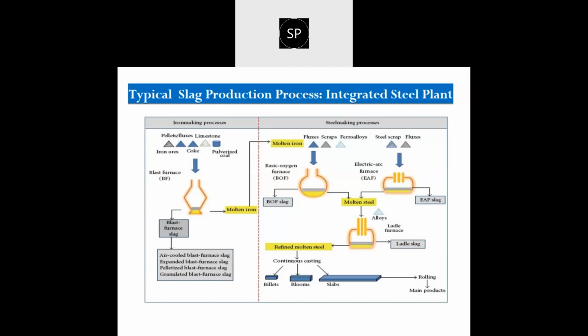In case you want to do cement concrete road work and ground granulated blast furnace slag is available nearby, then you can directly mix this material as a replacement of ordinary Portland cement inside the concrete mix, and you can prepare your M40 grade concrete accordingly. So this is one of the major applications of blast furnace slag. Besides that, the GGBFS, ground granulated blast furnace slag.